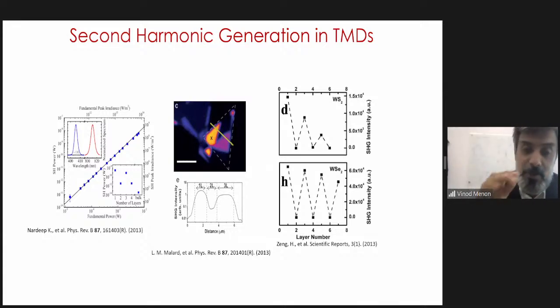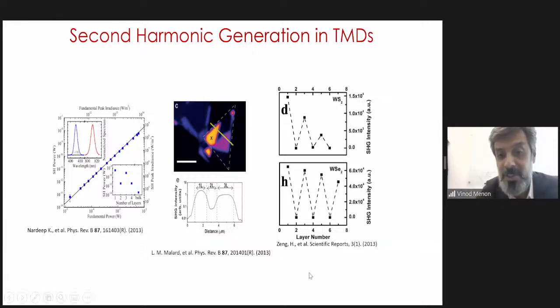So if you take these 2D materials, they have some very interesting property, which is that in the monolayer limit, in most of these materials that I was just talking about, the inversion symmetry is broken. So you get a nice second harmonic signal. You go to the 2-layer system, then they're on top of each other, and you don't get second harmonic signal. In fact, that is shown nicely here.